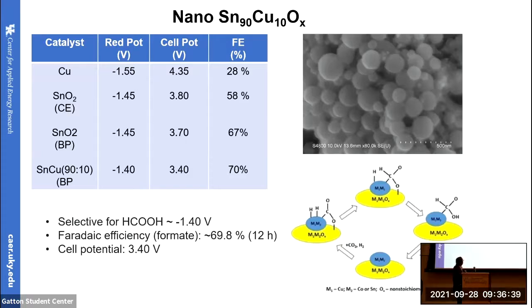Going from copper to the tin oxide composite, we see that the cell potential is very low. Lower cell potential means we apply less energy and still get more product, so it is energy efficient. Faraday efficiency is also good, and the reduction potential is going from negative 1.40, meaning we are getting formic acid at lower reduction potential. This is the reason for selecting the bimetallic catalyst. This process is still going on.